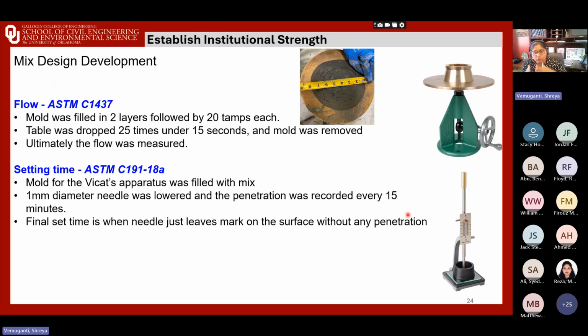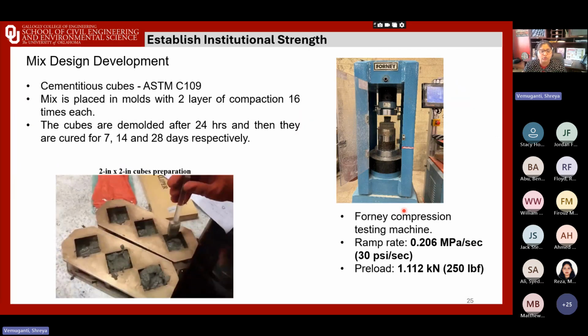One of the key challenges in both these aspects was balancing workability, but also strength, right? So the next process we did, in parallel, was to make sure these two material properties were in line with the compressive strength. So there were some baseline compressive strength results that we established, and how flow and setting time can be achieved for those compressive strengths. Our goal, yes, is very strong mixes, but it's also important to see this three-dimensional problem with pumpability, buildability, the flow, the strength. So there are several parameters that are coming into play all together.